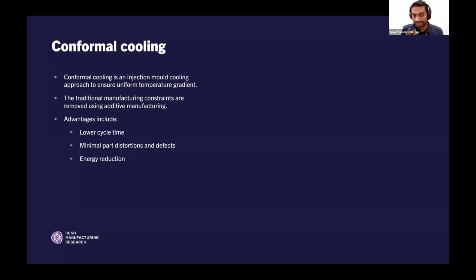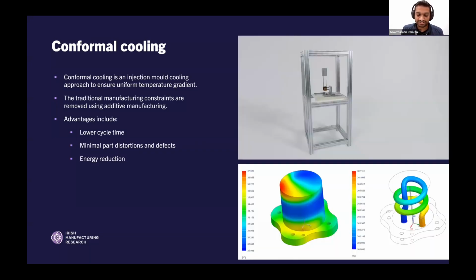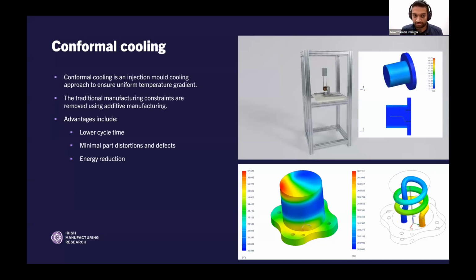Of course, we use simulation in finding out the conformal cooling channel performance, but how do we know if the simulations are right? That's where we have to validate the model. We have a test grid in IMR where we heat a test coupon to a prescribed temperature. Once it's heated to that temperature, it shoots out, and the cooling channels within the test coupon cool down the part. We measure the temperature over time and compare it with the simulations that are run using the SimCenter 3D thermal flow model. Once we validate this simulation, we can be sure that it can be translated to the actual part that we are going to investigate.